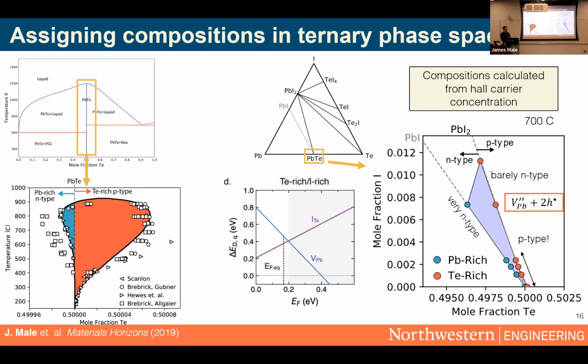And I didn't get into that part here. So that's a whole important aspect of the P-type lead telluride. But the N-type samples seem fine. So it's likely due to the vapor pressures in the phase equilibrium you're in that kind of suppresses loss of material. And I'm sure they lose a bit, and the people on here from JPL probably know way better than I do how much it loses, but in my experience, it's not quite as bad.